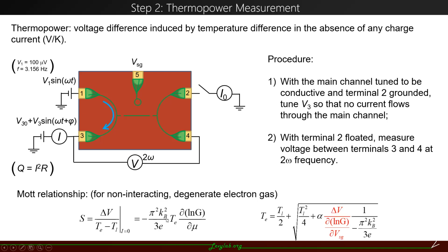Here we'll try the Mott relationship, which states that the Seebeck coefficient is proportional to the temperature and proportional to d log G / d mu, the energy derivative of the logarithm of the conductance. If the Mott relationship applies for a case, then we can calculate the electron temperature by measuring the thermal voltage and measuring the electrical conductance. And then we can put it back to calculate the Seebeck coefficient.